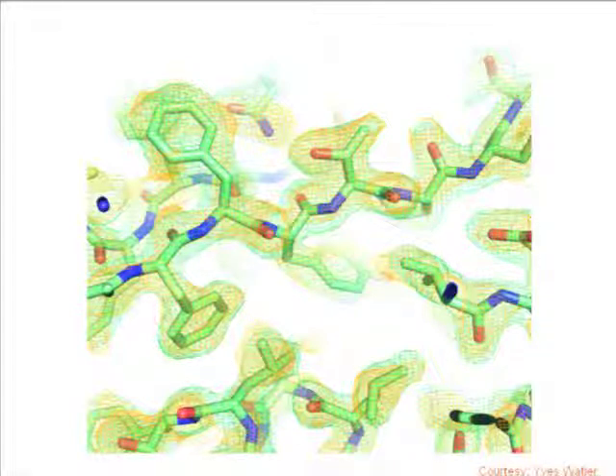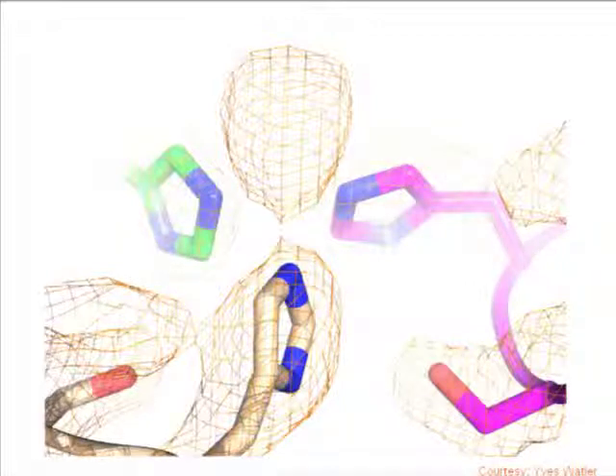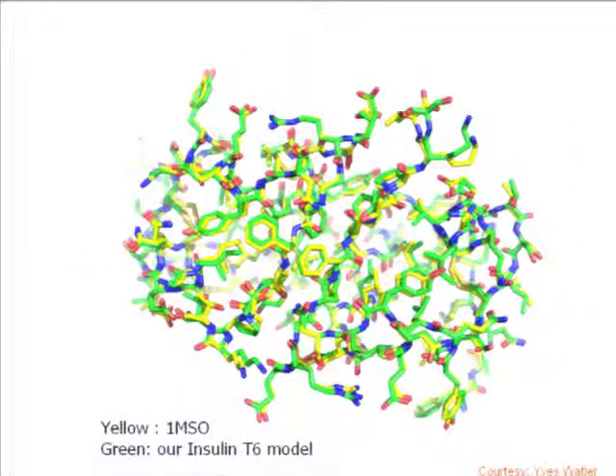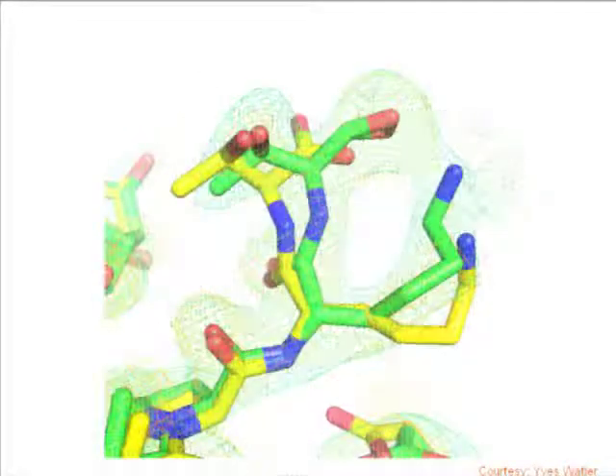So they approach single crystal limits, they are not broken, they are not as biased, and I have to say we don't work just with difference electron density maps, but we mainly use total omit maps, which are much less model biased. So the density was really high quality. It immediately showed where the zinc atom should be positioned. And when we compare the structure which was solved and refined from powders with a single crystal model, the agreement was pretty good. Here in yellow is the single crystal, green is the powder model. So within the resolution limits that we have in powder diffraction, this case was successful, and of course it was a test case.